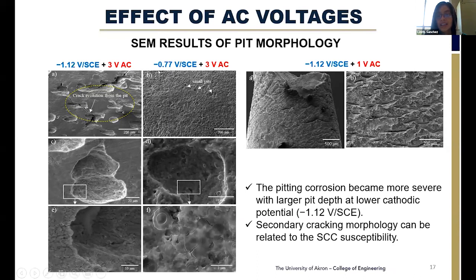In addition to that, I found secondary cracking in the sample under 1 volt AC. So this is related with the susceptibility to cracking that the sample has with AC voltage.